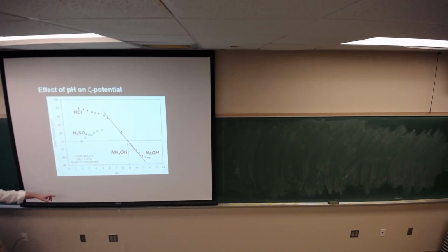This last thing you'll see here says a 10 millimolar potassium chloride background electrolyte. Okay, so what we do is when we measure zeta potential, you do it in the presence of a background electrolyte. So what that means is that you actually have ions potentially added that would be considered an indifferent electrolyte. So potassium chloride fits that bill. So does potassium nitrate. And technically, it would have been better to have used potassium nitrate.